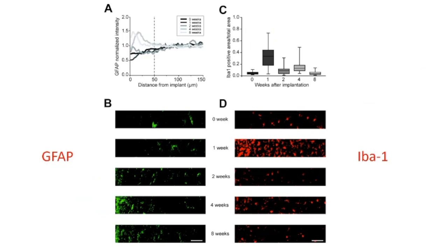So while we have discussed why carbon nanotubes would represent a great scaffold for neural regeneration, we still must consider the biocompatibility of this material. To study the biocompatibility, the 3D mesh of carbon nanotubes was implanted into the brains of 4 adult male rats. Initially, the scaffold was immunolabeled for the glial fibrillary acidic protein, or GFAP. The GFAP fluorescence intensity peak was limited to a relatively restricted reactive area of less than 20 micrometers, which is smaller than other artificial implants which average a reactive area of 60 to 100 micrometers.